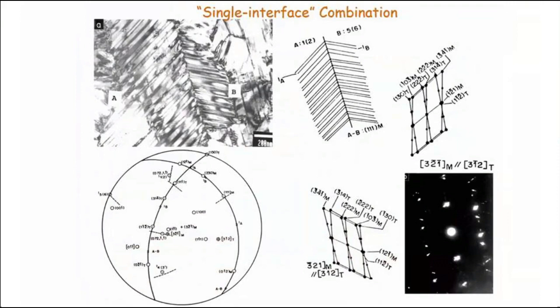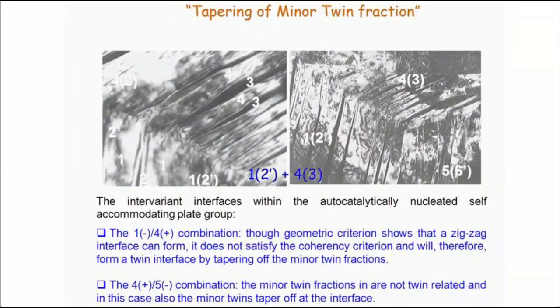And here I present the first case where there's a single interface, a situation in which both the major and minor twin fraction are twin related. And you can see this, it looks very much like the figure which was shown before, a very ideal case where both are twin related. And there are only 4 such out of the 13 unique combinations.